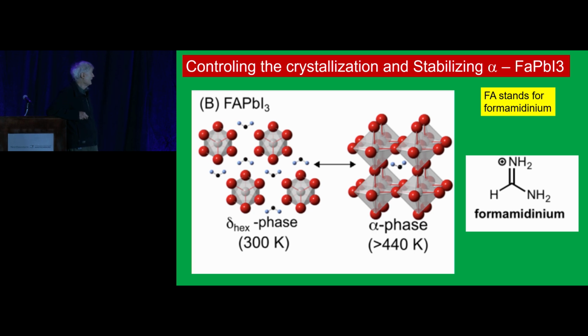But a lot of research has been invested into avoiding that phase transition, which turns the black phase into the yellow delta phase. The delta phase is a different structure. It's a one-dimensional structure with hexagonal symmetry, and the octahedra are face sharing. So it's a different structure than these corner sharing octahedra you see in the alpha phase. And so there was a lot of research interest in maintaining the alpha phase stable.